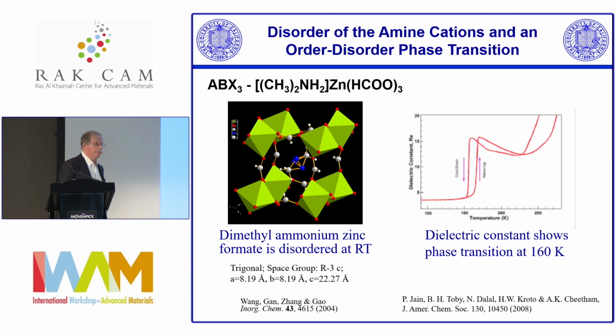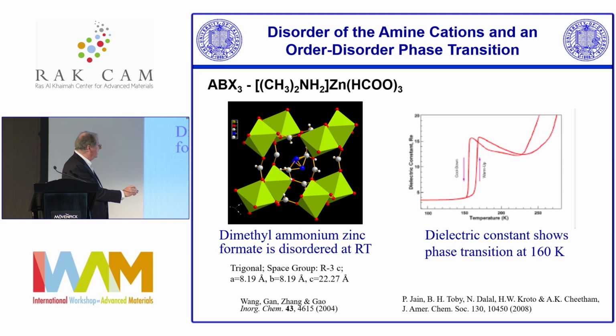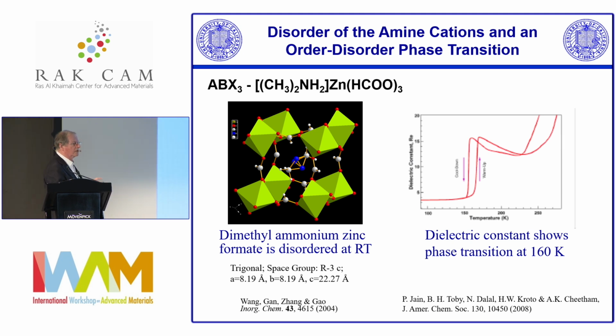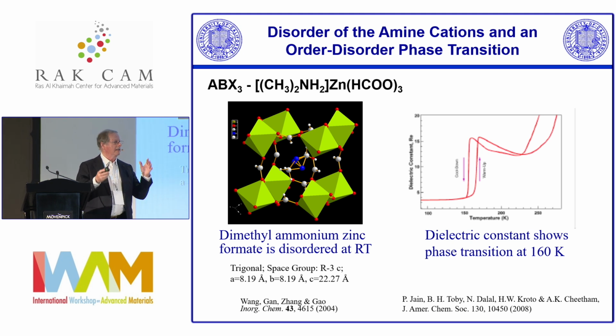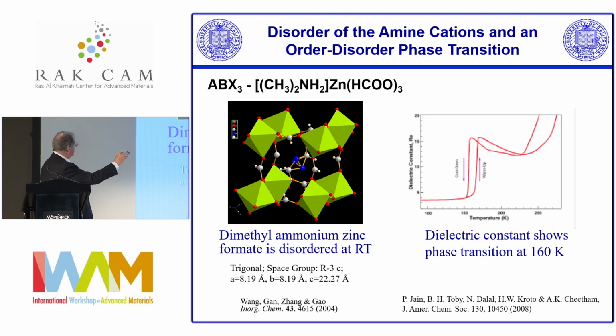We actually made this by mistake one day in the lab. One of my students, who was a wonderful chemical engineer but not a great synthetic chemist, made this material, which was the one that Song Gao had first made, the zinc compound. And we thought, how exciting, when I looked at this crystal structure and I said, that's a perovskite. I was not aware of Gao Song's work, but by the end of the afternoon, of course, we knew that we were not the first people to do this. But what I did notice was that the amine in the cavity, this dimethylammonium, was rotationally disordered in three equivalent positions around the three-fold axis.